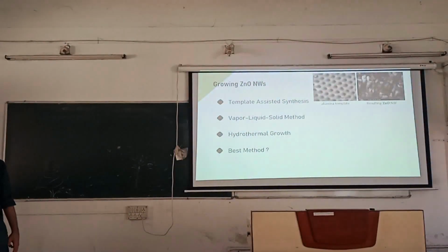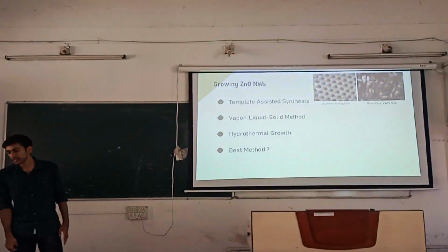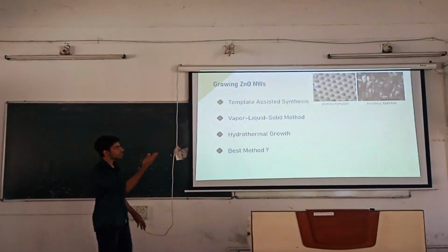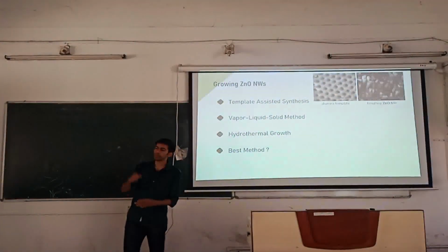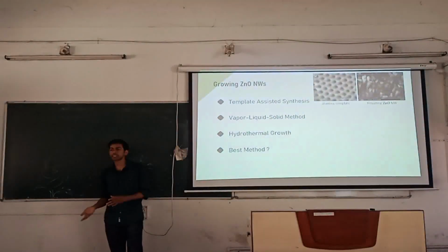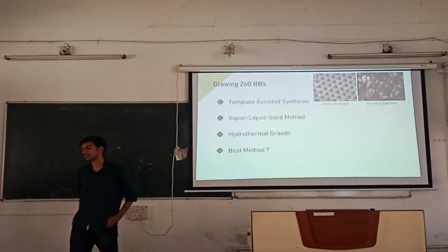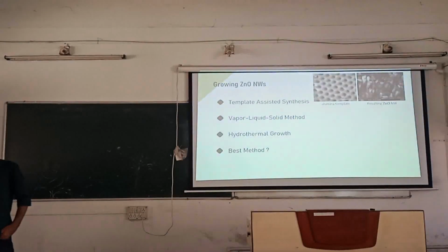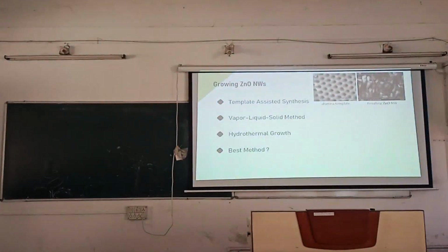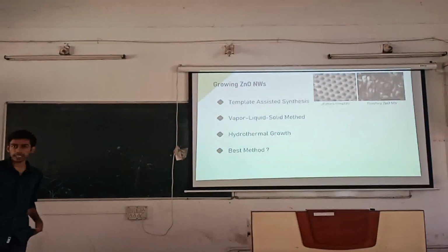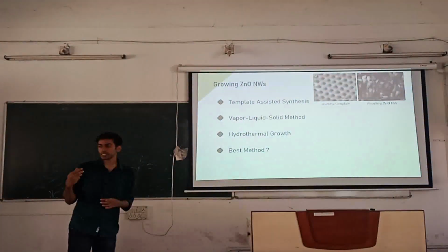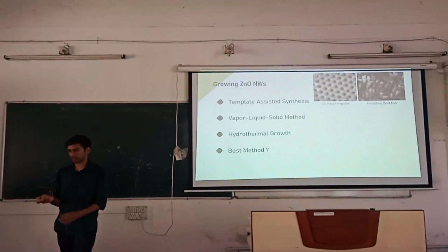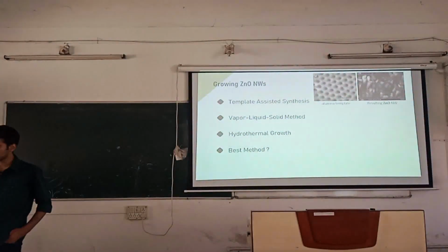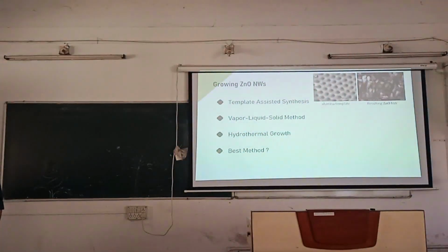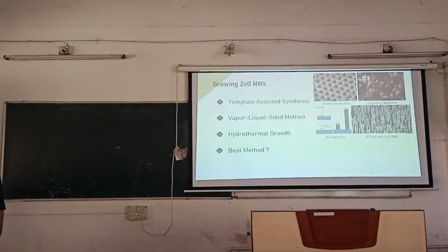So in template assisted synthesis, what we do is we take a anodic alumina template with so many holes in it, and we just apply pressure and put in zinc and heat it, and zinc will turn into zinc oxide in presence of air. It's a very lame way of doing it because we don't have orientation at all in the crystal. Like a zinc oxide can go inside the hole in any orientation. So all crystals won't be oriented along the 002 axis plane. So that is bad. So we won't be using template assisted synthesis.